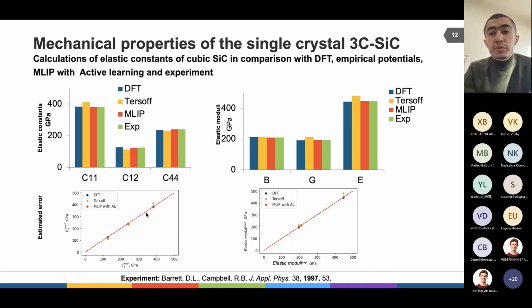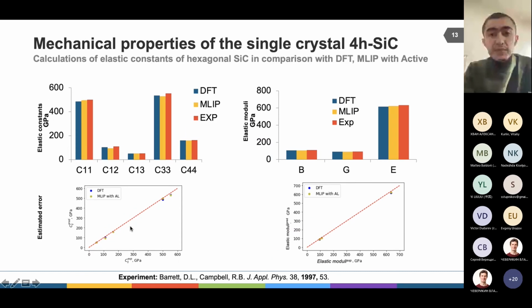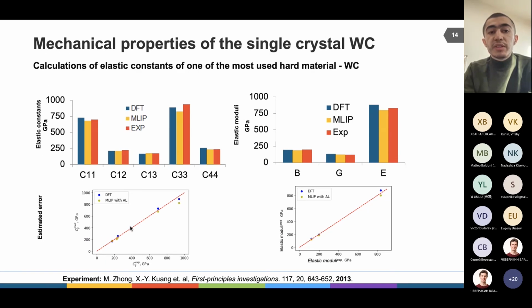Here are results for 3C cubic silicon carbide, with comparison with DFT and empirical potentials and machine learning interatomic potentials with active learning. And as you can see, in this case the machine learning interatomic potentials also showed the best results. Here is another phase of the silicon carbide, and here are the results of calculation of elastic constants for one of the hardest materials, tungsten carbide. Here you can see elastic constants and elastic moduli by using different methods like DFT and machine learning interatomic potentials, in comparison with experiment.